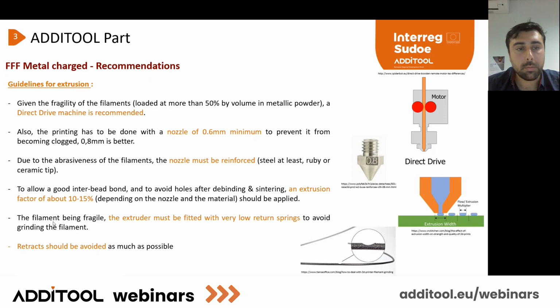Okay, so the filament being fragile, the extruder will be fitted with a very low spring force, not like what we see with a classical extruder. When we push the filament like this, the material is very fragile. It's a little bit like butter. We grind the filament very easily, so it's not necessary to have a big force to push the filament.